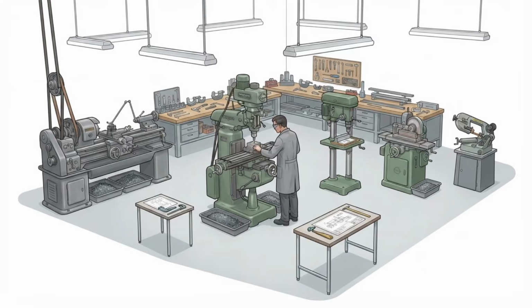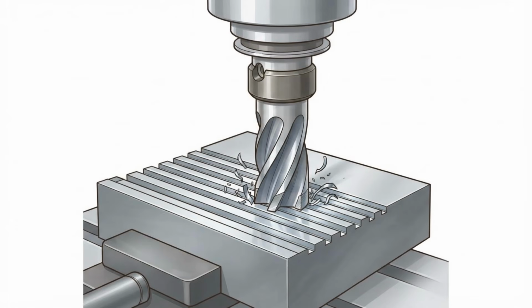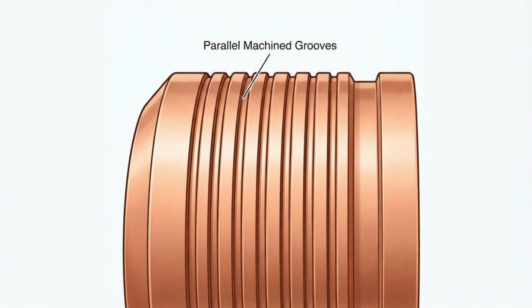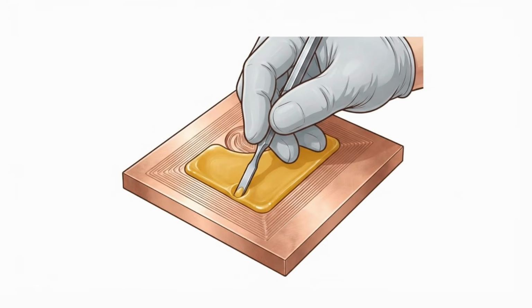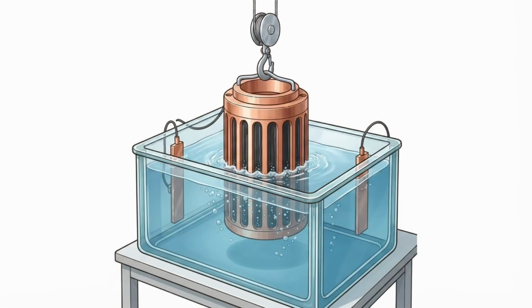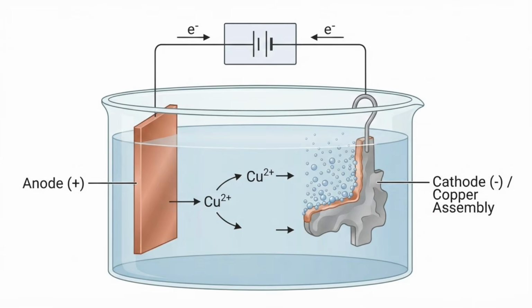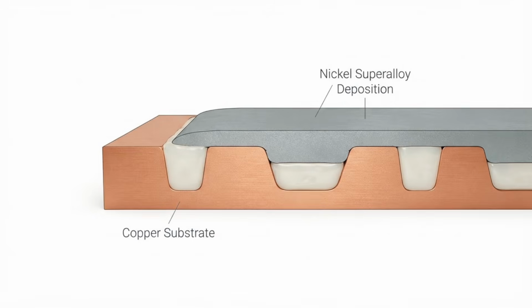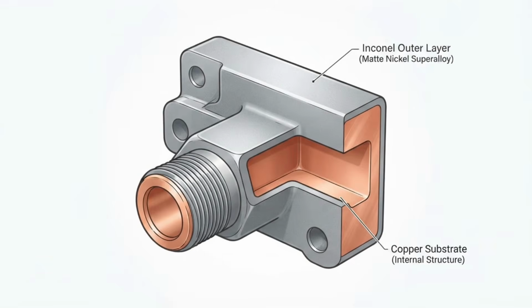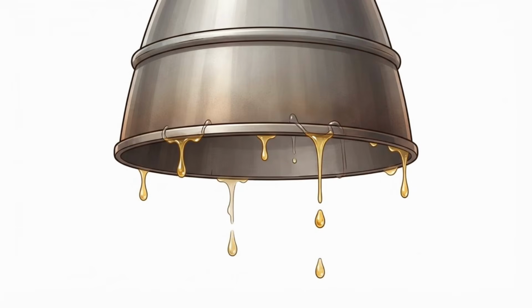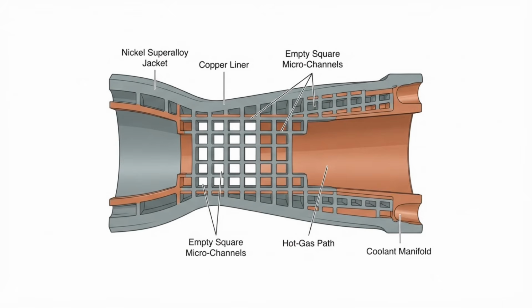Historically, manufacturing a regeneratively cooled chamber involved milling hundreds of tiny parallel vertical grooves into the outside of a copper liner. These grooves were filled with wax, and the entire assembly was submerged in an electroplating bath, where a thick layer of a heat-resistant nickel superalloy, like Inconel, was plated over the copper. The wax was then melted out, leaving behind a network of hollow microchannels hidden inside the walls of the engine.